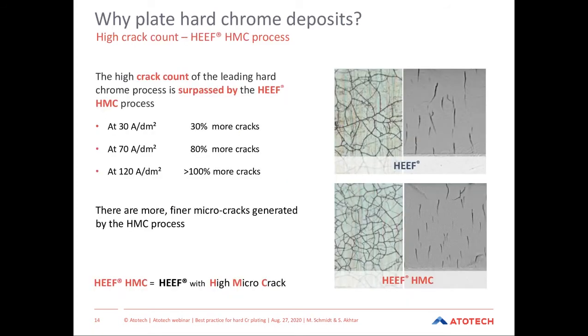With the traditional chrome plating processes, we observe a drop in the crack count numbers as cathode current density increases. So to counter this effect, Atotech has developed its HEEF HMC process. And HMC stands for high micro cracks. With the HMC process, we can achieve a plus 30% higher number of cracks compared to HEEF 25 at a given nominal 30 amps per square decimeter.